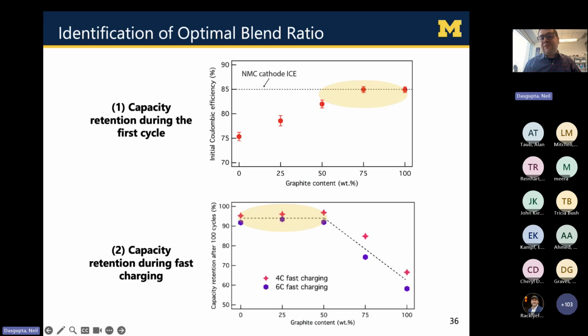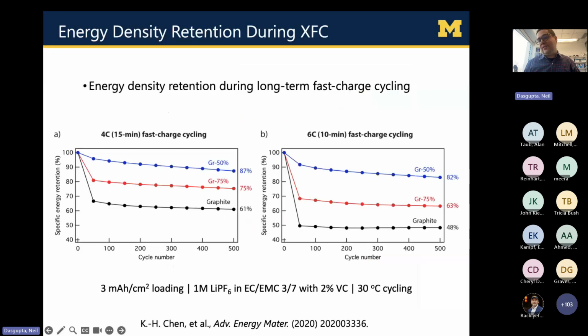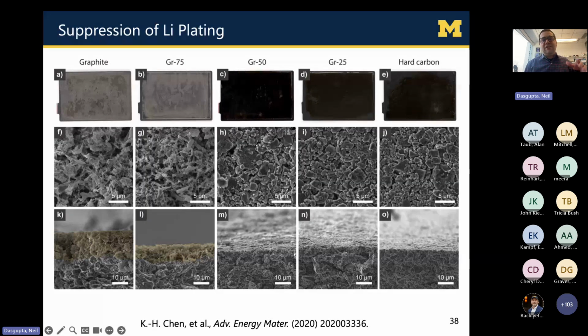On the other hand, by the time I get to 50% graphite content, I can now maintain very high capacity retention both during 4C and 6C fast charging without lithium plating on the surface. So here shows a comparison of the capacity fade during 4C or 6C fast charging. The black lines are the pure graphite. If I just blend 25% hard carbon into the graphite, I see that immediately I can see a huge jump in capacity retention. And we found an optimal blend ratio of about 50-50 to balance off the energy density and power density trade-offs. And once again, you can see the trends here.